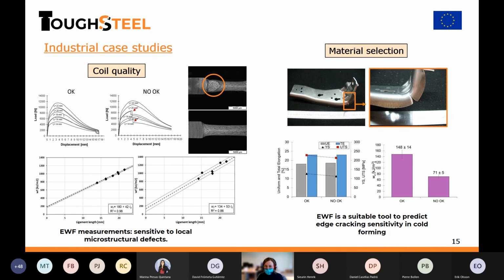Then the last case study shown here, you can find more in the user guideline, is from an aluminum 5000 aluminum alloy. From two different batches, they found that one batch had some cracking problems when forming, but they made a purer alloy for this aluminum, and this problem was solved, but they wanted to know why. So they performed some traditional tensile tests, and they found that the conditions for these two materials were similar, but they couldn't understand why there was some difference in this cracking process.